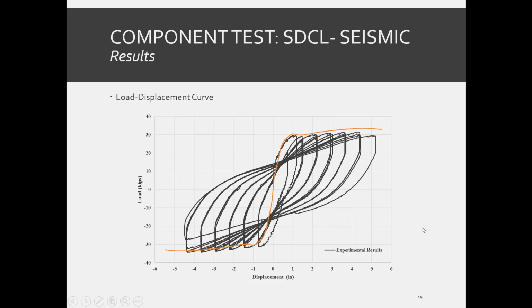This figure represents the load displacement curve. For each displacement, 3 cycles were run. We observed that there is no substantial strength degradation up to the last cycle. We can see the specimen shows sufficient ductility and symmetric behavior. The results are also compared with moment curvature analysis, the red line, and we see a very good agreement between them.